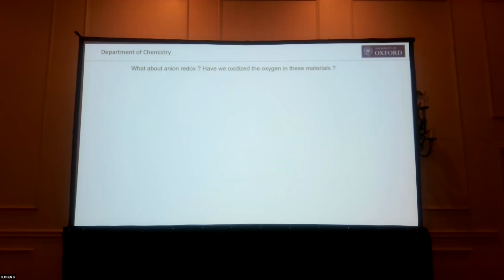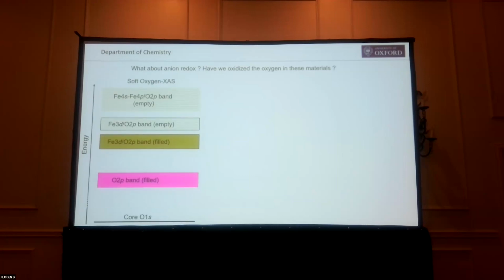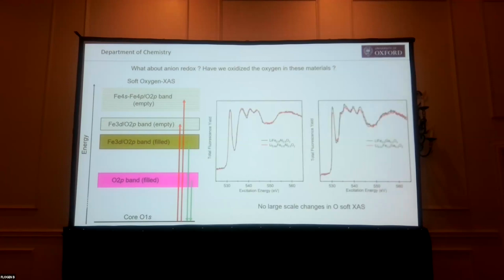What did we take them from? Well, we can look for oxidized oxygen by using soft X-ray absorption. So what we're going to do, although what Ken was talking about before, is we're going to use soft X-rays to excite electrons from the core 1s orbitals of our oxygen to any orbital band that has any oxygen character. Basically, the electrons are going to get excited up into the hybridized iron 3d oxygen band, and then the hybridized iron 4s4p. And once we excite an electron from this core oxygen 1s orbital, what then happens is electrons in orbitals that have oxygen 2p character will then drop back down and emit a photon. We'll catch those photons, and what we then do is plot out the total fluorescence here. So basically, plotting out the total number of photons as a function of excitation.